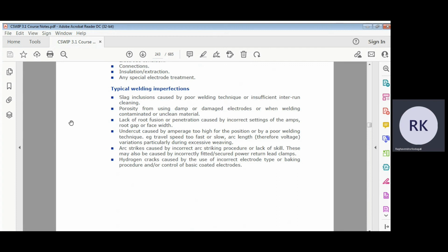Lack of root fusion and penetration caused by incorrect setting of amperage, root gap or face width. So if your root gap is not good and the root face does not have the right width, then there will be a lack of fusion and or lack of penetration. It also happens due to incorrect setting of the amperage. Then undercut caused by amperage too high for the position or by poor welding technique. So undercut, as we said, if the amperage is too high, undercut will come. Amperage too low, also undercut will come. So that is the reason. And travel speed, if it is too fast, these are the things which we already discussed earlier.